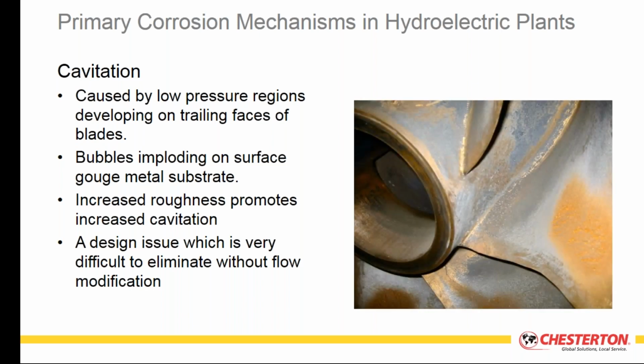When you see cavitation occurring on a hydro runner, the surface looks like it has been frosted or etched. It typically is in fairly localized regions near the trailing edge of the turbine runner blade, on the low pressure side. These are areas where we want to be able to address, because they are areas of high likelihood of damage occurring in your hydroelectric plants themselves.